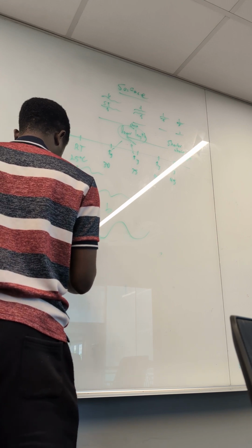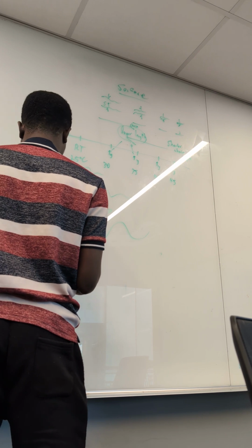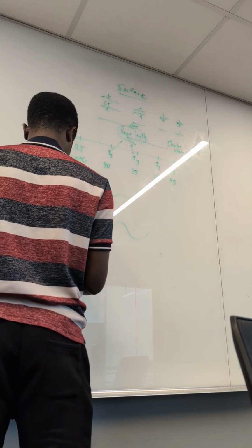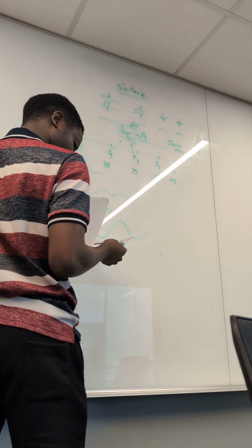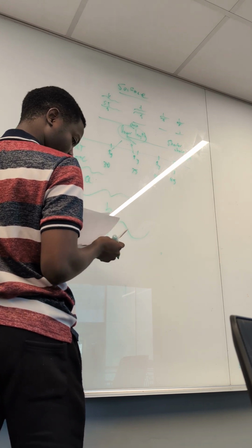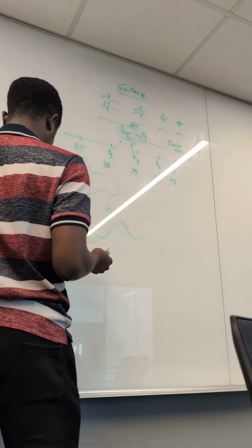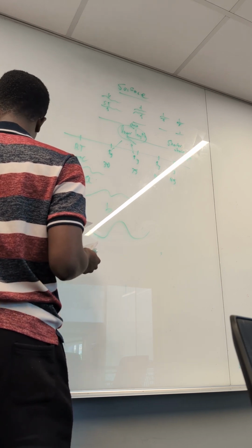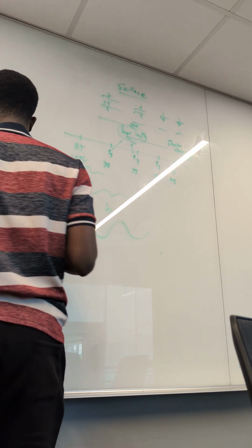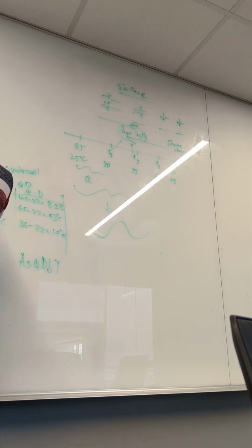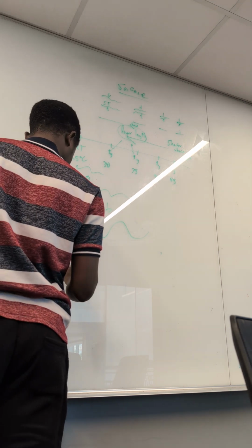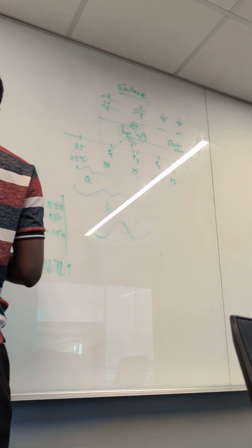This graph right here is basically telling you that this is the film thickness, okay? And at some point, the wavelength goes to 0, which means we get no wrinkling. For all the films, this happens at a certain thickness; it doesn't happen at 0. This green, I believe, this diamond pattern one, was the longest chain length, and that happened at the highest thickness.